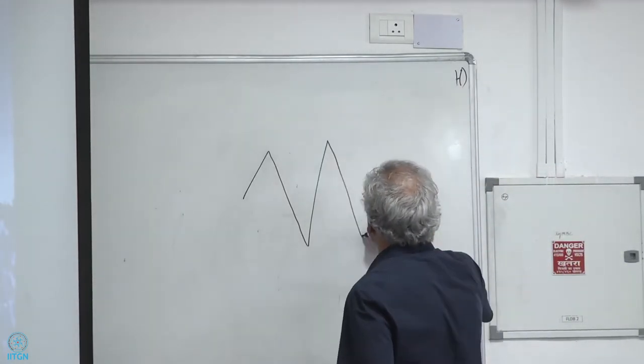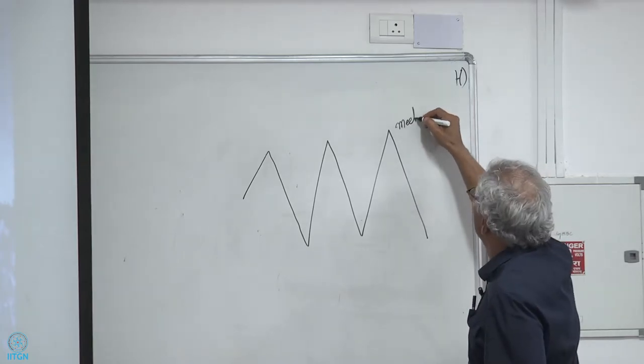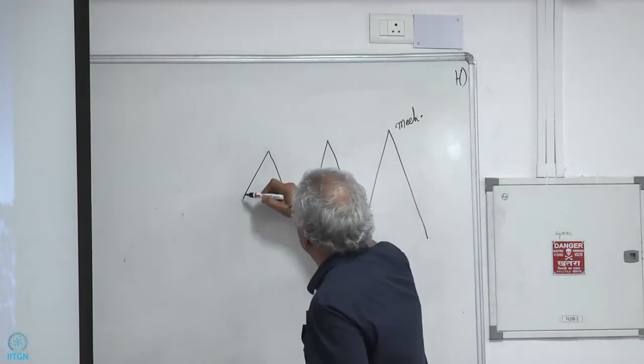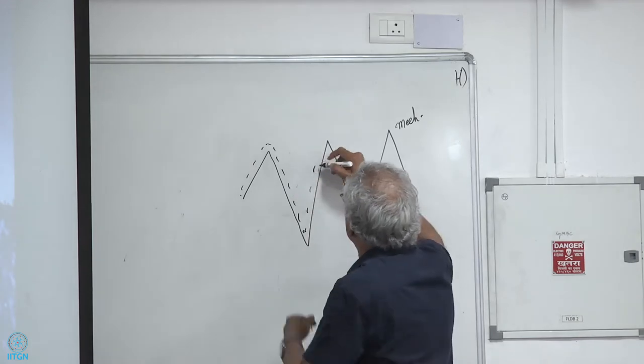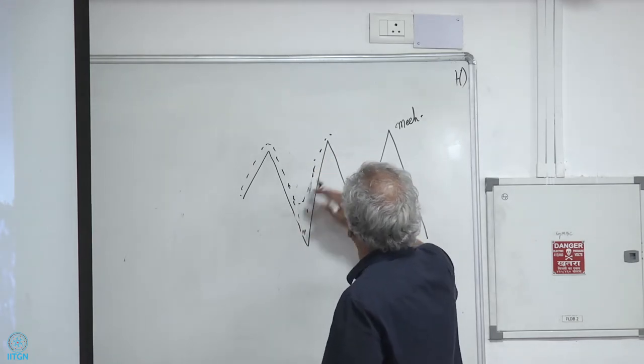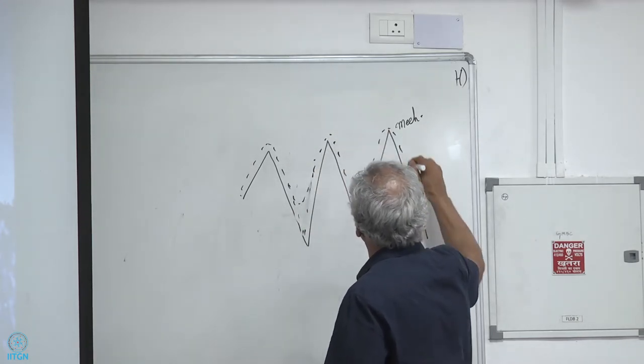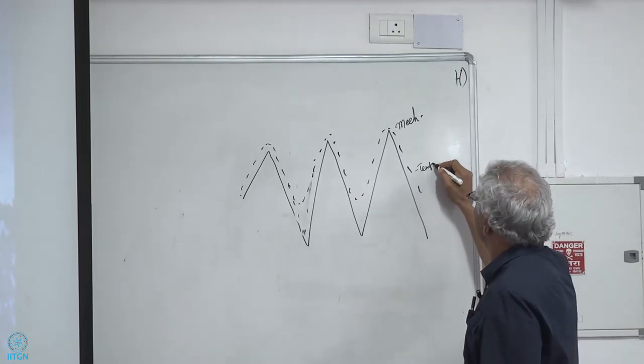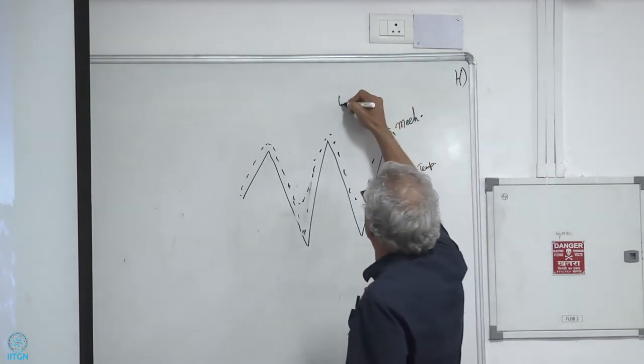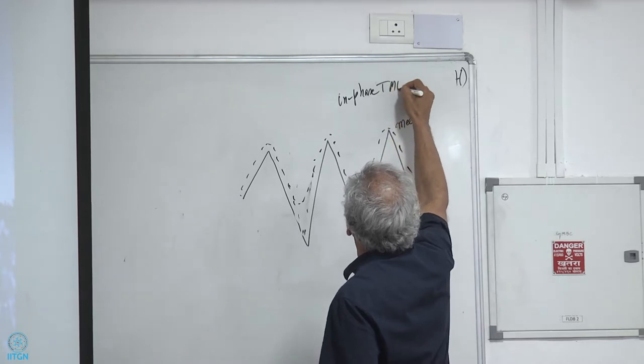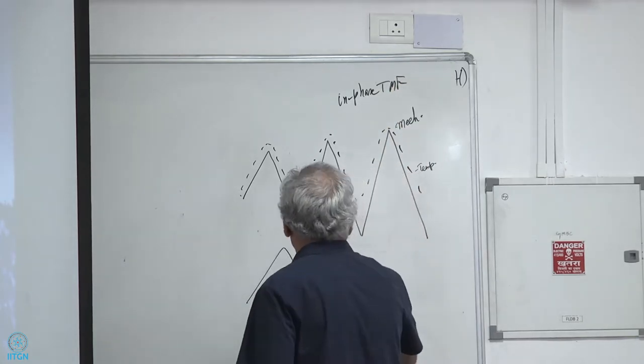So if this is a nickel-based superalloy, and you're doing this test at a high temperature where there's a possibility for oxidation, there's a possibility for creep also, but not necessarily dwell fatigue in this sense, then you may be doing a creep fatigue test or a creep fatigue oxidation test.